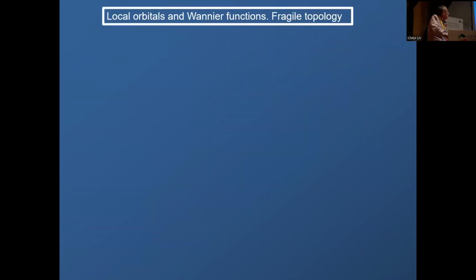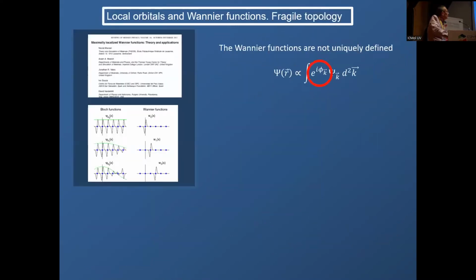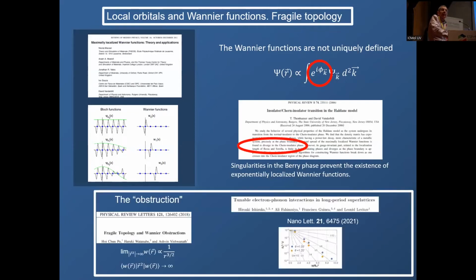So in a few words, the problem is that these bands in twisted bilayer graphene, like Landau levels, are topologically non-trivial, and because of that, mathematically, the Wannier functions you can define do not decay exponentially like a nice local atomic orbital. They have a power law tail, and how relevant that power law tail is or not is the whole gist of this obstruction problem, which is being intensively debated by all theorists interested in topological materials.